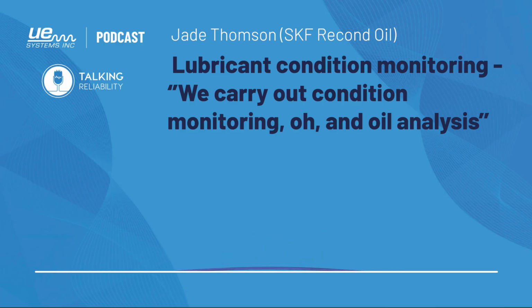Ideally, we need to know, is it a helical gearbox? Is it worm and wheel? What size is the gearbox? How much oil's in there? All that information allows us to determine correct alarm sets, but also in your equipment manufacturer's manuals, you should ideally have some alarm sets that they set, because they will know specific ratios of wear metals that you will see. We need to know the oil type that should be in there.